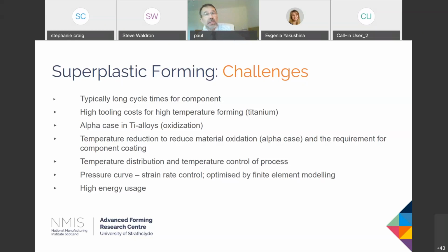The other thing is, if you're actually making a new part using superplastic forming, you will need to do a bit of work to optimize your pressure time control curve. That's the rate at which you put the gas into the part in order to reduce the forming process as much as possible in terms of the time. But that's fairly easily done these days by finite element modeling. If we can jump to the next slide, Steph.